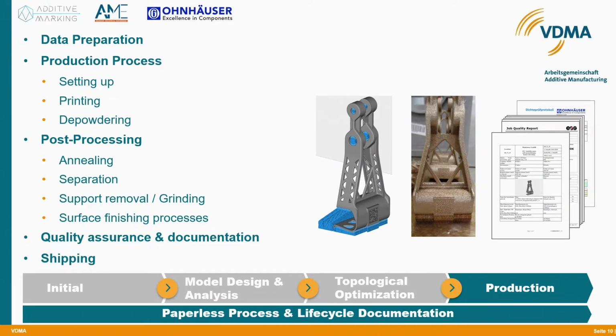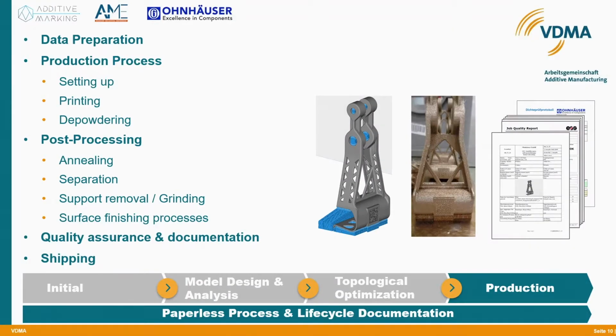After printing and depowdering, the build platform is removed. The extracted powder can be reused after a refreshing process. As a result, very little waste is generated during the build process. Before the printed build platform continues the process chain, the parts are checked for printing defects. The high process temperatures result in high residual stresses in the parts. These must be removed in an annealing process to ensure the dimensional accuracy of the parts. After annealing, the parts are separated from the build platform by a bandsaw and assigned to their individual orders. In this step, the test samples are removed and tested. After this test has been successful, the remaining parts will be approved for further processing.